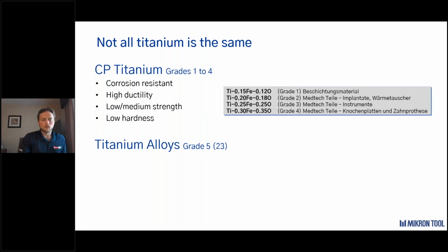As we look kind of the differences, right, grade 1 through 4, these are going to be the most likely materials we're going to run into in the bone plate category. Typically, these are not going to be an external part. We may find some, call it consumer goods that are made out of grades 1 through 4, but typically these are going to be implantable plates used for not only their biocompatibility, which matches with grade 5, but also the slight flexibility that grade 1 through 4 allows. A little bit of a more forgiving material.